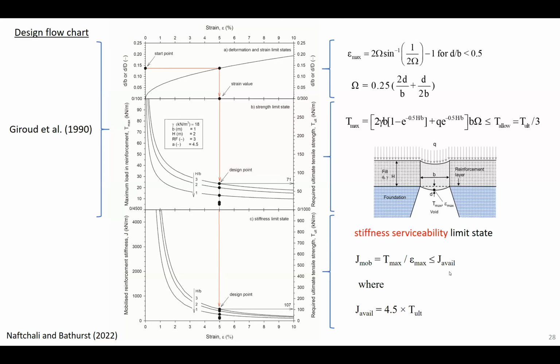And again, if I don't have product specific data, I can estimate what that available stiffness is by finding the coefficient of proportionality between secant stiffness and the ultimate strength of the material. And that'll at least get me into the ballpark in order to look at this particular limit state. And the thing is, depending on which method you use, of which there's about 4, you can construct these flow charts and evaluate each of these limit states. In the paper by Naftchali and Bathurst last year, we provided those flow charts for different design methods.